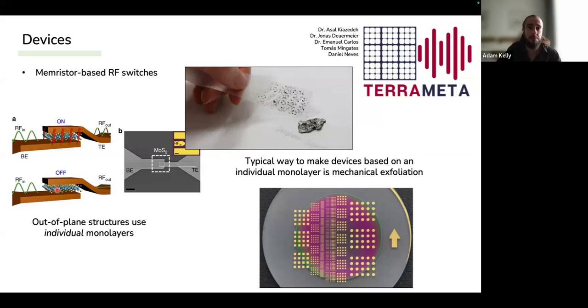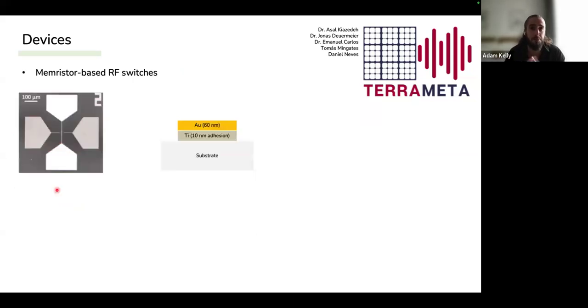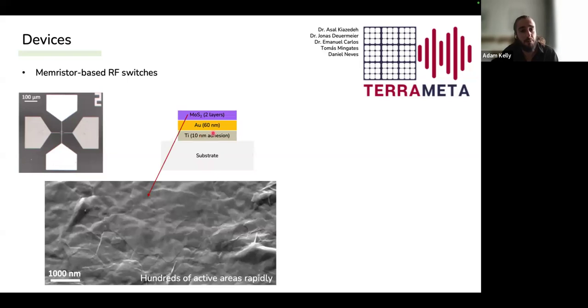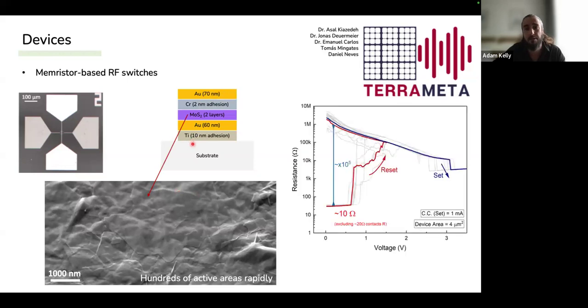So a way to do it is by solution processing, using some of the techniques that I've told you. We took a substrate, silicon dioxide. We deposited our adhesion layer of titanium and gold. And then using that liquid-liquid interface method, we globally coated the entire substrate in 2 layers of MoS2. And then we deposited our electrodes on top. We were able to do this deposition in a couple of minutes. It was rapidly done. And then by depositing the electrodes on top, we had a memristor structure with high yield.